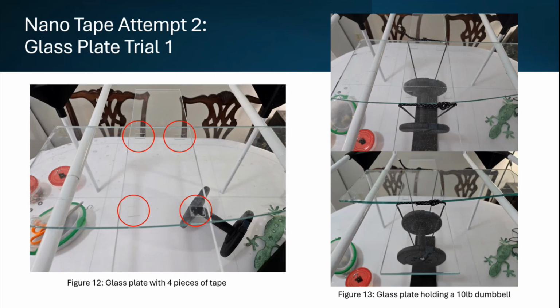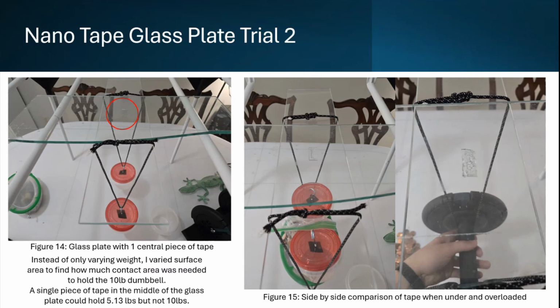Okay, my attempt two, I used 4 pieces of tape and held a 10-pound dumbbell from it, and I held it just fine. So I don't want to go higher than 10 pounds with dropping a 10-pound dumbbell onto my counter. So I decided to reduce the area of the tape. So my second trial was 1 piece of tape in the middle. I held the 5.13 pounds fine, but when I added the 10-pound dumbbell, it started producing a bunch of bubbles, and you can see that in the right picture. Once all those bubbles formed, very quickly the glass dropped from the setup.